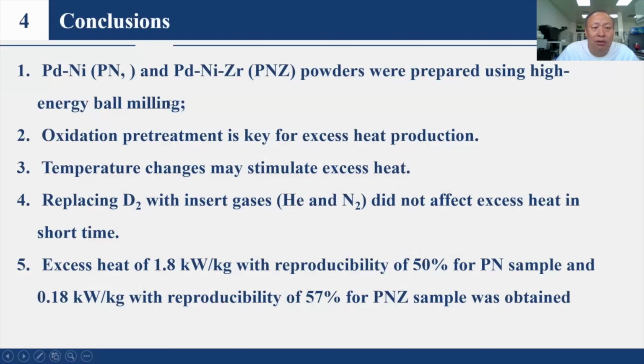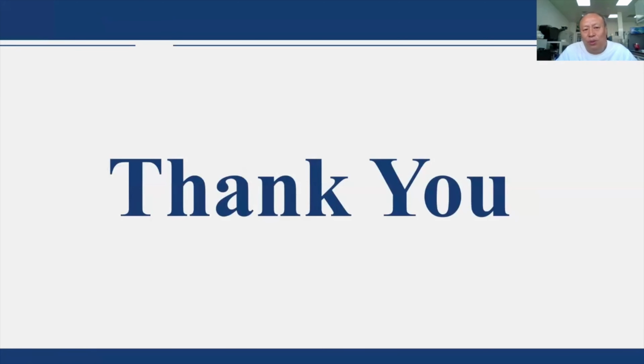This is a conclusion. Firstly, the palladium, nickel, and palladium-nickel-zirconium powders were prepared using high energy ball milling, and oxidation pretreatment is key for excess heat production. The third is that temperature change might stimulate excess heat, and four is that replacing deuterium with inert gases did not affect excess heat in a short time. And five is excess heat of 1.8 kilowatts per kilogram with reproducibility of 50% for PN samples, and 0.18 kilowatts per kilogram with reproducibility of 57% for PNZ samples. This is all our report. Thank you.